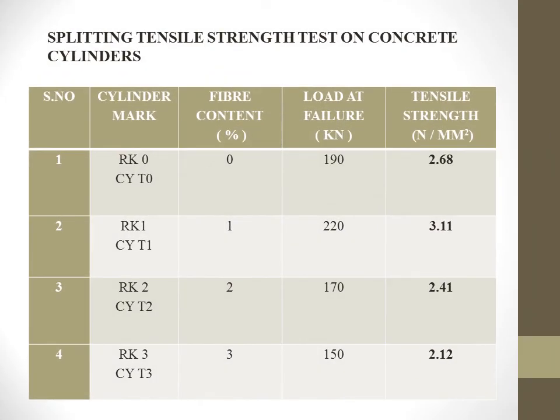Then we had also done split tensile strength on cylinder specimens. The split tensile strength with nominal mix was found to be 2.68 Newton per mm square, and with 1% addition of bamboo fiber, the tensile strength had increased from 2.68 to 3.11 Newton per mm square, and then it had slightly decreased with 2% addition of bamboo fiber to 2.41 Newton per mm square. The tensile strength had decreased to 2.12 Newton per mm square with 3% addition of bamboo fiber.